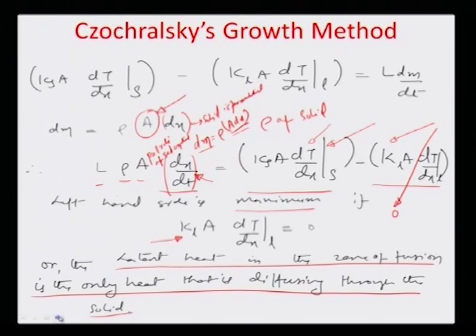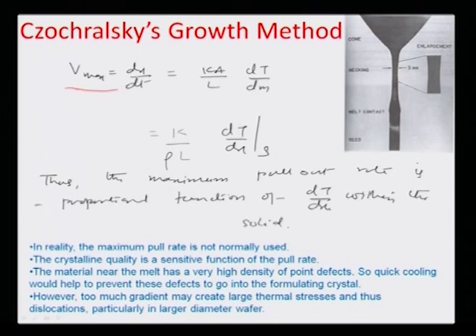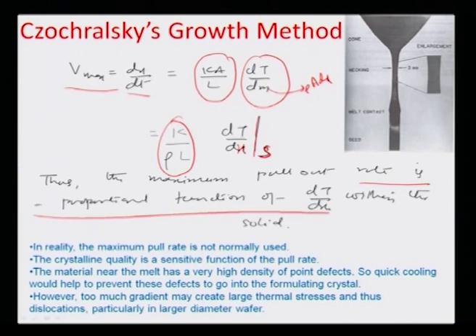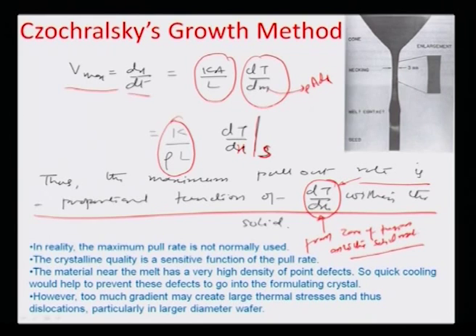And so this is a one dimensional case where you have the maximum pull rate V max represented by kA/L times dT/dm, or k divided by rho L. We are just putting the value of dm here, rho A dx, times dT/dx, and this dT/dx, mind you, is in the solid domain as the heat emanates from the zone of fusion into the solid. So the maximum pull rate is proportional to dT/dx, the temperature gradient from the zone of fusion onto the solid material. One may argue that if you have a very large dT/dx, it would result in maximum yield or maximum pull rate, which is actually not the case.